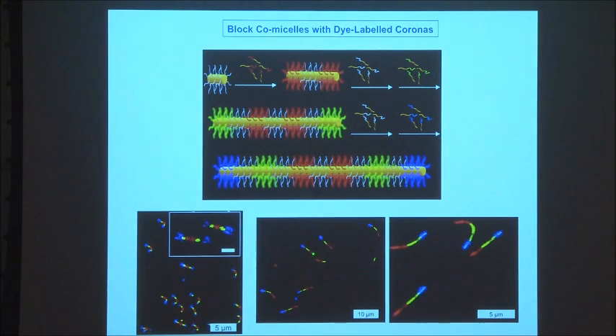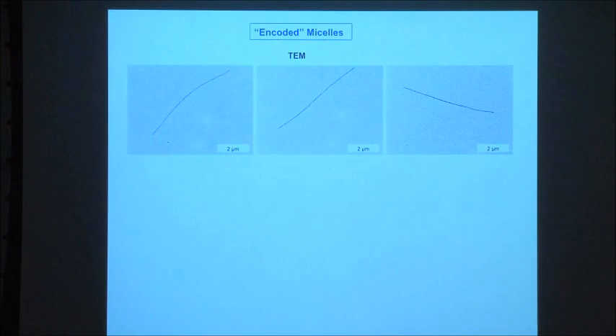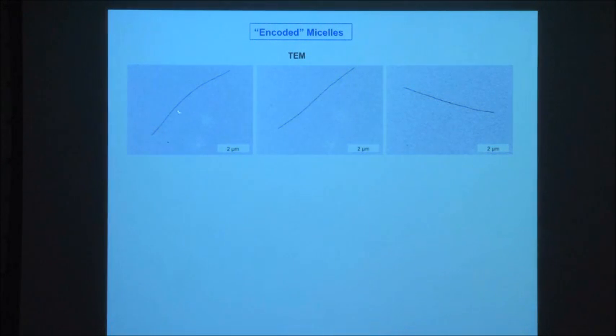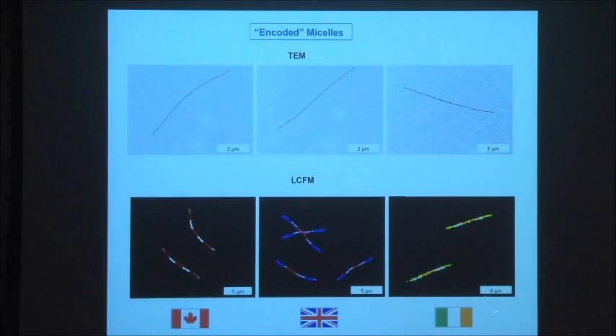So you can make these nanopixels, which you can visualize using confocal fluorescence microscopy. And these are ones of this type of structure. These are some of the ones where they've been grown in one direction here. So these are centrosymmetric, these are non-centrosymmetric. These are quite interesting as encoded micelles. So for example, these 3 micelles look exactly the same by electron microscopy, but they're actually encoded with the colours of the Canadian, British and Irish flags here, just using the fluorescent dyes. So they're quite interesting materials.